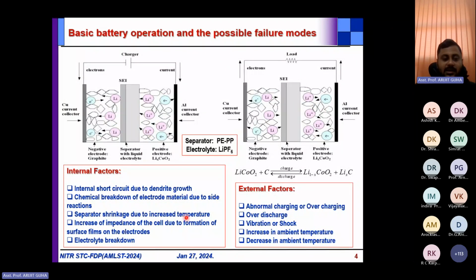So there are certain internal factors and external factors which are responsible for battery degradation, and the so-called failure mechanisms are accelerated. Here I have listed some of them. There can be an internal short circuit due to dendrite growth. Dendrite growth is when, on this SEI layer, there is a formation of a metallic lithium crystal kind of structure, and eventually it will try to puncture the separator and connect the anode with the cathode, causing a short circuit. Due to that short circuit, it can catch fire, just like the fire incidents in the Samsung Note 7 battery or in Ola electric bike. So this is one of the internal factors which can eventually boil down to a thermal runaway kind of